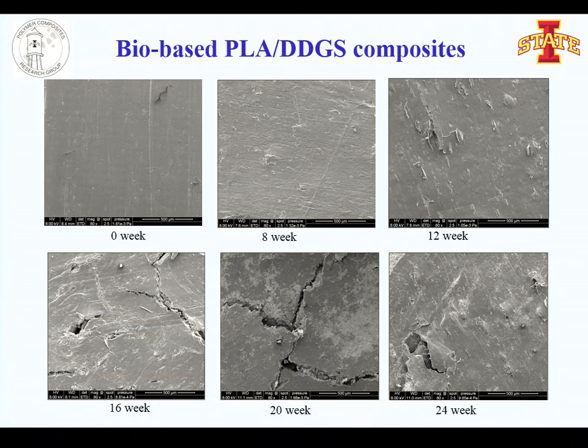What's causing degradation? Is it microbial, or is it photo degradation? What's causing it, I think, is started by hydrolysis, and then by microbial degradation. So it's a combination we're going to have to deal with, right? Well, this is in the soil afterwards. No argument, but one of the questions we're going to have to take a look at is that different mixes have different microbial rates, and different mixes have different hydrolysis rates too. So that's why I'm trying to figure out which one's which in those cases. So none of this is happening during the container life? Perhaps on the inside. And it can go through to the outside on some of the less stable materials, but it's much slower when we're growing the plant in there, because it's only coming from the inside toward the outside. These are buried in the soil here.